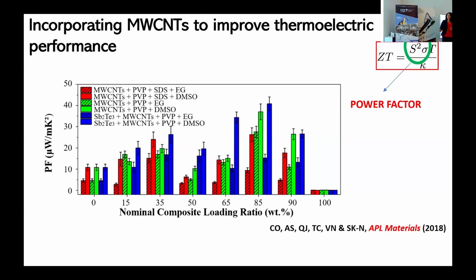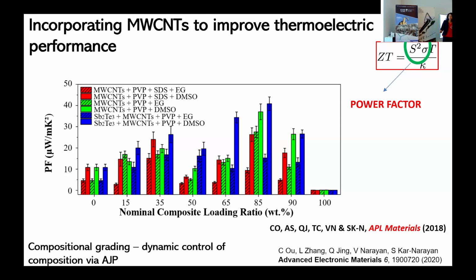And what he found was that by changing the loading ratio, the amount of the inorganic versus the organic component, you can start to find compositions with the largest power factor, which is what people working in thermoelectrics are interested in. And again, it's also possible to induce compositional grading. So rather than have one material with one composition, you can spatially vary the composition, which for thermoelectrics is quite useful, because rather than having one material with a fixed ZT at one temperature, you can design the material to maximize the ZT as you go along the temperature gradient. So there's some nice work which Canlin had done.